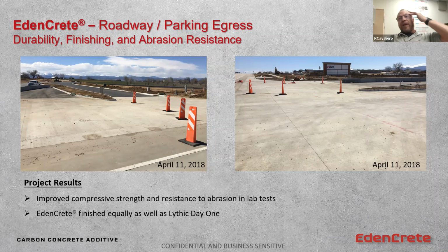So what we see, Hector, is that the fresh properties are improved. If you need a 6-inch without EdenCrete, you could do it with a 4-inch with EdenCrete. A truck pulls up and it's a 5-inch, and they add 10 gallons of water. If it's a 4-inch, they add 20 gallons of water. When trucks pull up with EdenCrete, they'll let it drop to a 4 and dump it out before they start messing with any water. If you need water, EdenCrete will help it take that water, endure that, give fewer color changes, and help you have a more consistent strength. But we're not going to require water as readily as a conventional mix would.